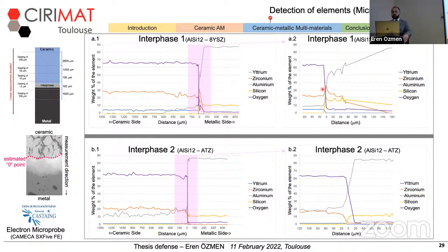And I want to come quickly to the interface itself. We see that the interface distance, which is observed in scanning electron microscopy, also corresponds with electron microprobe. And what's interesting, just after the 0 point, the estimated 0 point, which is the border between ceramic and interface, yttrium, which is indicated with blue in the graph, disappears from the composition, going to 0 directly. We observe this for the second interface as well. So yttrium was also not detected in this method.